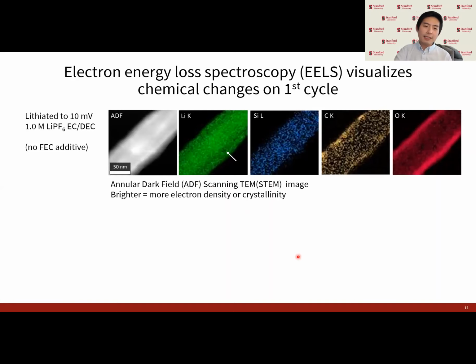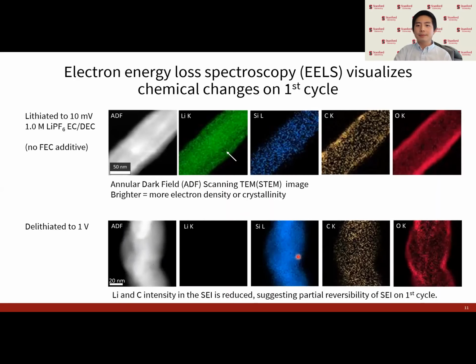But what's really interesting is if we take these silicon nanowires and then delithiate them. So if we take the nanowires through a full cycle, we can see that lithium is removed not only in the silicon core, but also along the outer surface where the SEI is. Additionally, the carbon counts across the nanowire become very dilute across the nanowire surface. And all of this suggests that there is some reversibility to the SEI on this first cycle. So people generally think of the SEI as sort of a statically growing or monotonically growing structure. But from this kind of TEM analysis, we can already see that the SEI is a lot more dynamic than that. And it can even exhibit some reversibility on this first cycle.